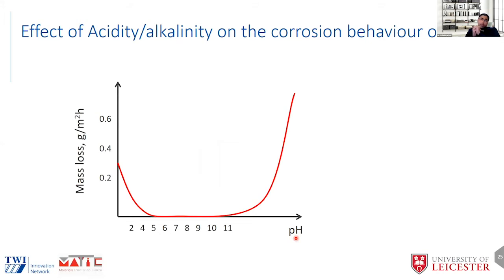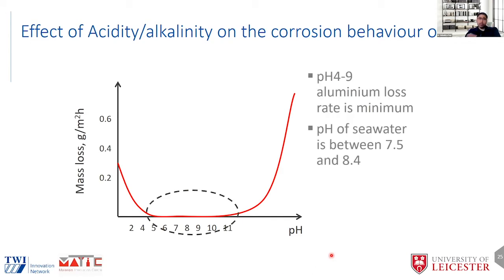In terms of the kinetics of corrosion of aluminium in different pH regions, we can again see that within this pH range, we have a fair bit of stability and very low loss or corrosion rate. So we are seeing that between pH values of 4 and 9, we see very little loss of aluminium. And knowing that the pH of seawater is about 7.8 to 8.2, we can be certain that aluminium is going to work in this system. So the self-corrosion of aluminium is very low, but what will happen when it is in galvanic contact with iron or steel?